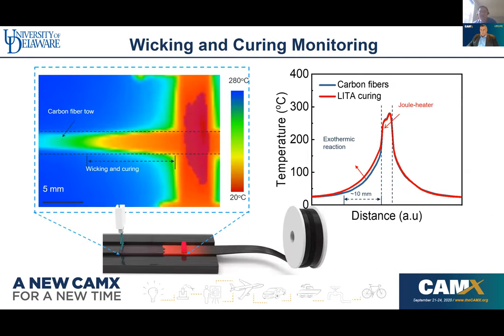And here we carried out the experiment by using the IR image to capture the temperature distribution. As we can see, right here is our hot temperature. We apply the heat to our carbon fibers, and in the horizontal direction is our carbon fiber filament, or carbon fiber tow. You can see very clearly a gradient thermal distribution from around 50 degrees C to a high temperature. And when we drop the liquid on the cold area, or the cold zone, we can monitor the temperature. On the right side, you can see the temperature distribution.